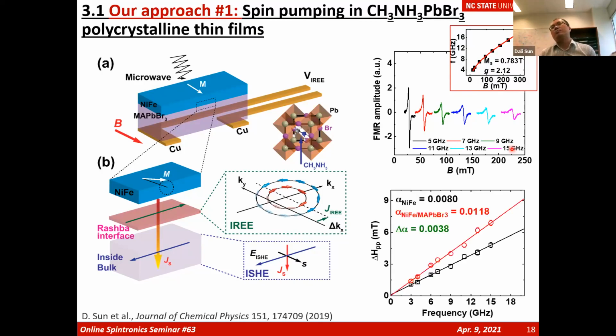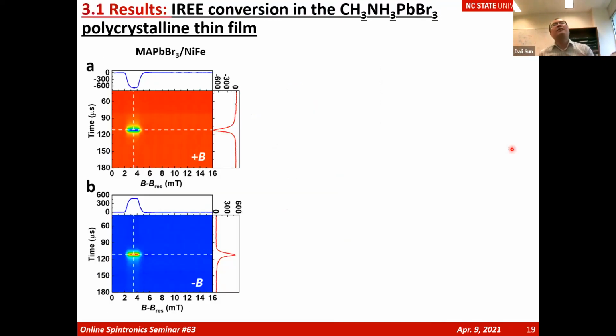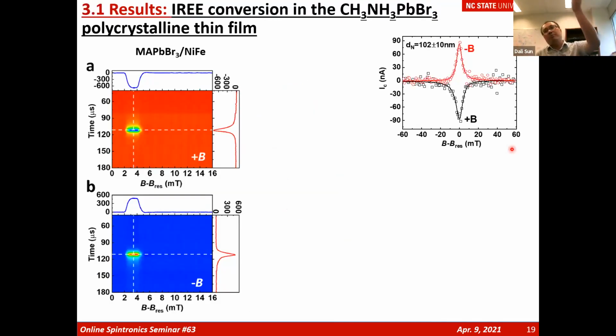By measuring the FMR responses, we see a clearly increased damping factor, indicating that the spin pumping method works. We really inject spin current into hybrid perovskite materials, even in the solution process, polycrystalline thin film. We are able to measure a typical ISHE response, which reverses sign when the magnetic field is reversed. There is a positive ISHE response in the microvolt range, giving us a pretty strong signal indicating that spin-to-charge conversion happens in hybrid perovskite materials.